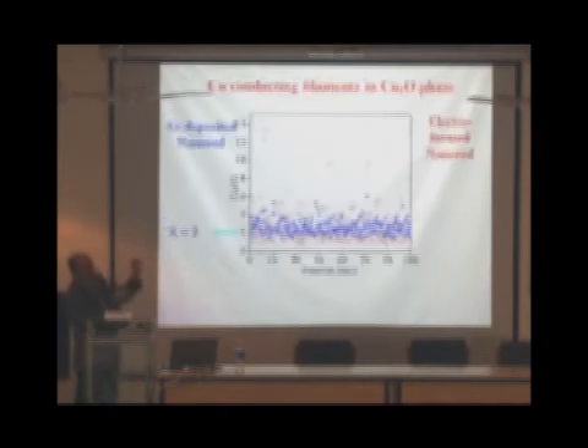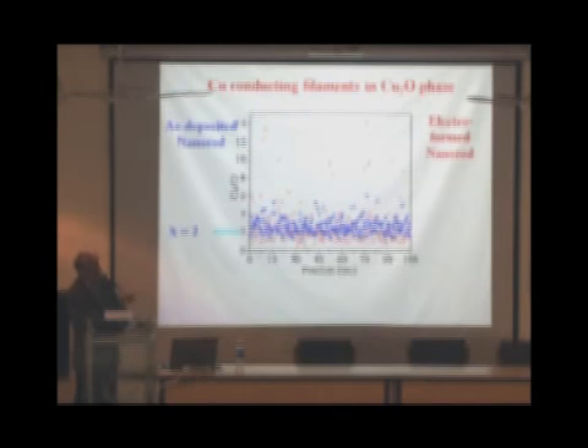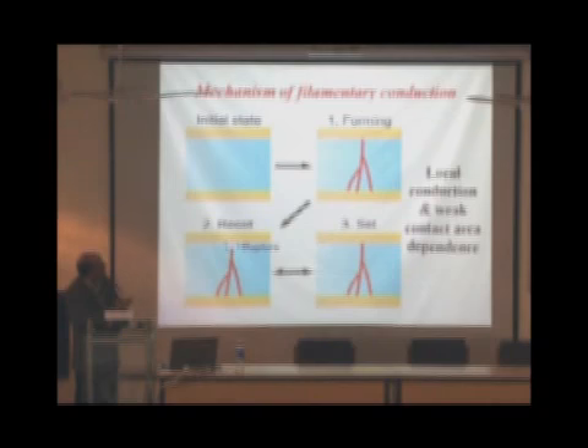And then we look at the compositional changes within one nanorod. So you can see that this is the diameter of the nanorod, which was around 100 nanometers. The blue dots show you the composition of copper and oxygen without electroforming, and the red dots are the composition after electroforming has taken place. And what we see is that after electroforming, there are certain points along the diameter where the composition has changed. What we understand now is that this has taken place due to the formation of some sort of a copper filament in the copper oxide, or a metallic filament in the oxide. So it's like a small fuse between this metal and this metal which has formed due to electroforming. When you apply the reset voltage, there is a small rupture of this filament and the device resistance goes back to the high resistance state.